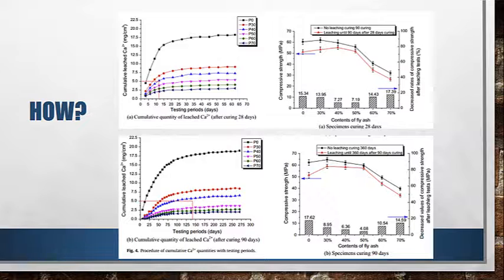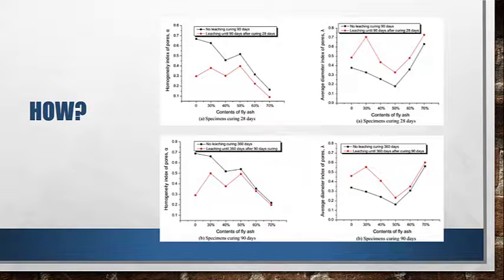Materials and methods. The chemical compositions of the cement and the fly ash are shown, as well as the cementitious materials and the mixture proportions. The water to cementitious ratio was kept constant at 0.35, and the fly ash content varies at 0%, 30%, 40%, 50%, and 70%, to reach a constant slump of 200 millimeters. Polycarboxylate superplasticizer was used at different ratios.